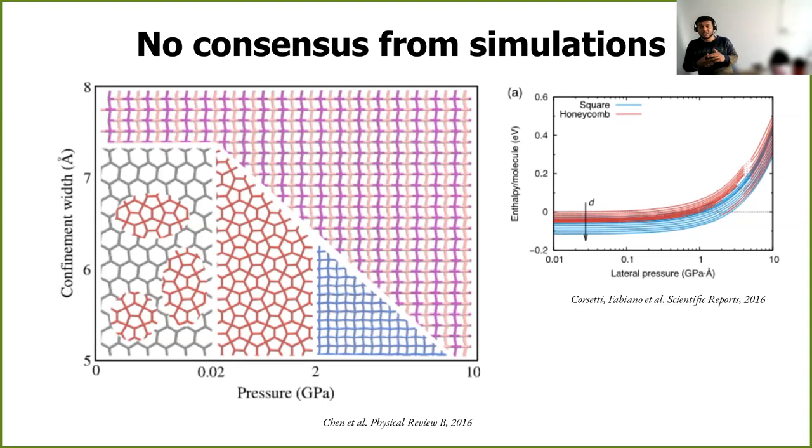like density functional theory, which is at least first principles, right? And it was not fitted to experimental data, at least some of them. So in this case, there's this nice paper by G. Chen from Angelos Michaelides' group from at least 7 years ago, maybe. And they found that using a particular functional, they have a hexagonal phase, which can be degenerate compared to the pentagonal phase. But after 0.02 GPa, you have a pentagonal phase, and then you have a square phase. And note that this was all performed at zero Kelvin, because of course, density functional theory calculations are rather expensive, or at least back then they were considered more expensive compared to the resources that were present, right?